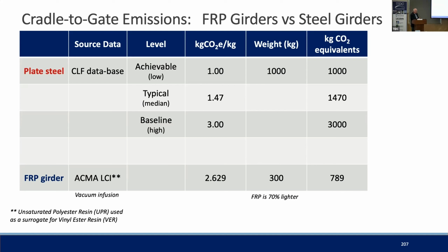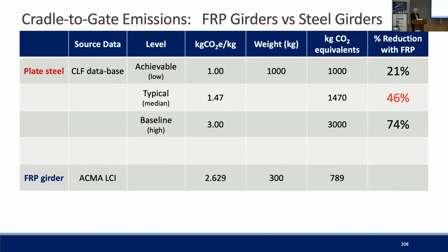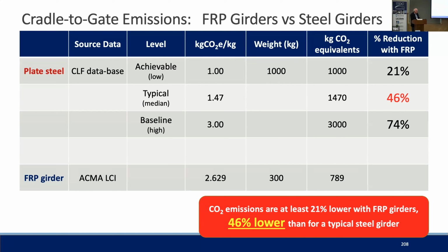But I have to make one assumption, because that life cycle inventory does not contain data for unsaturated polyester resin or for vinyl ester resins. So I have to use the data for unsaturated polyester resins as a surrogate. As a chemist, I'm perfectly fine with that assumption. Again, FRP is 70% lighter. You do the math, and this new column shows you even more impressive reductions in FRP relative to steel. It shows you that CO2 emissions are at least 21% lower with FRP girders, 46% lower than for a typical steel girder.